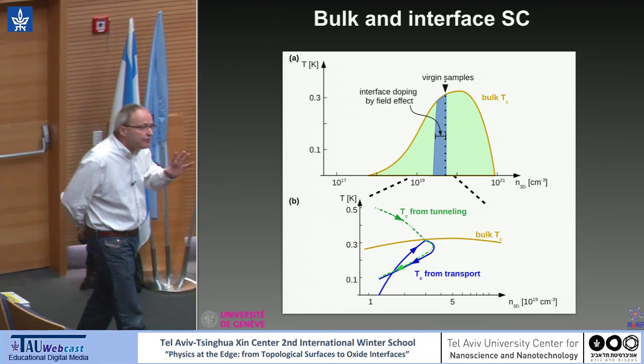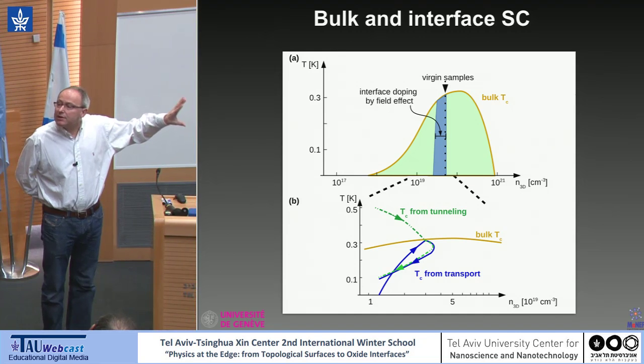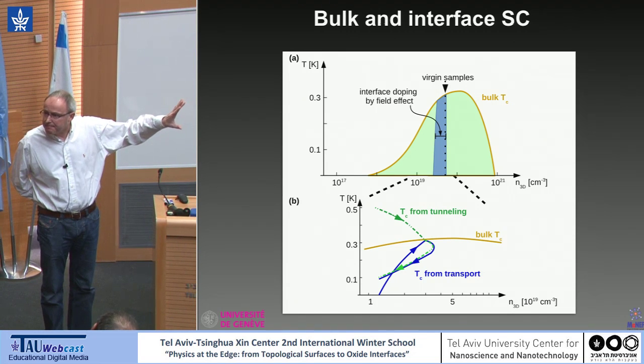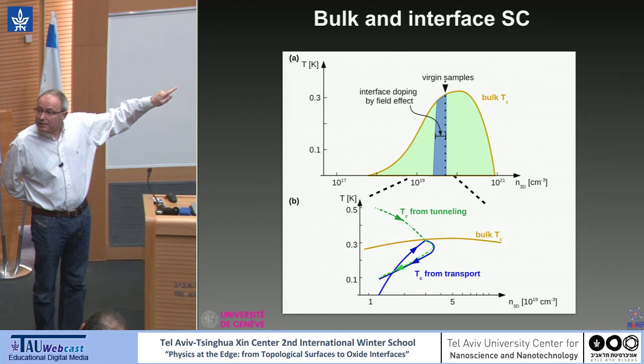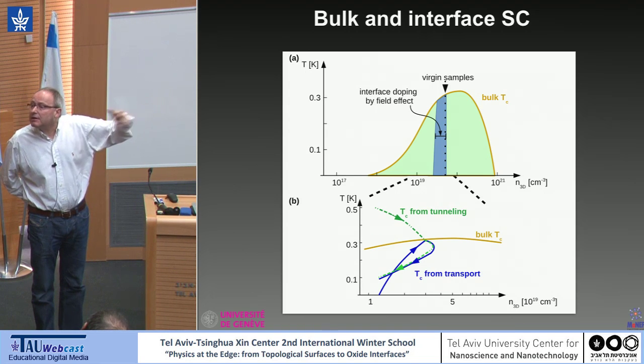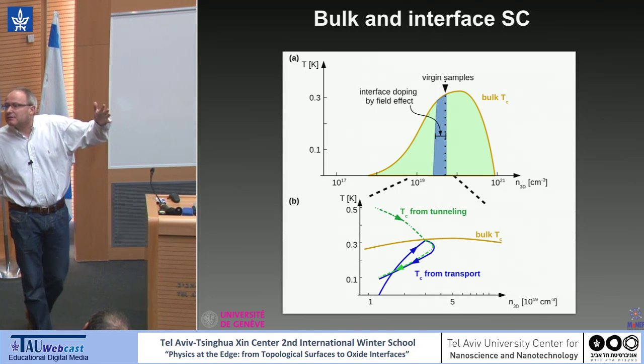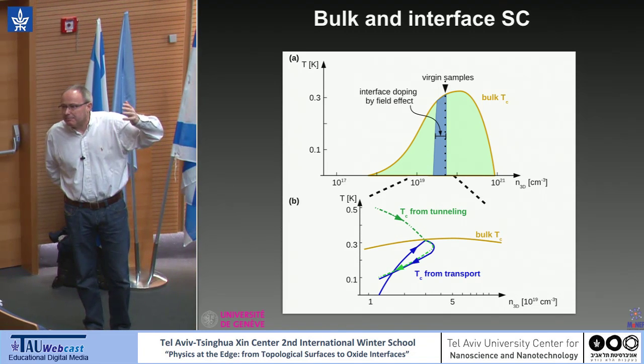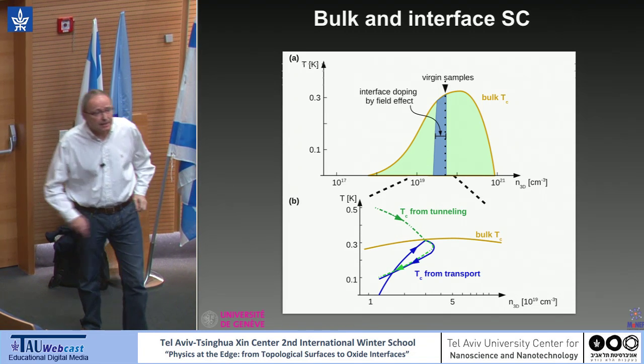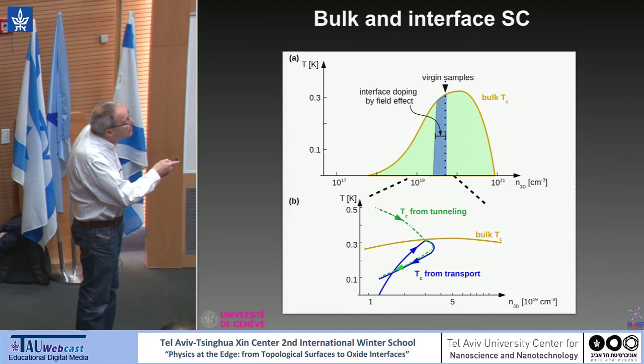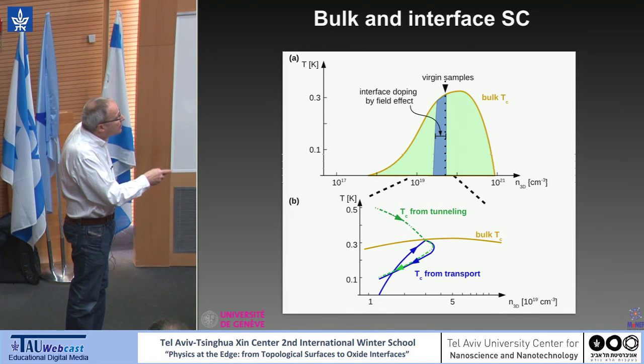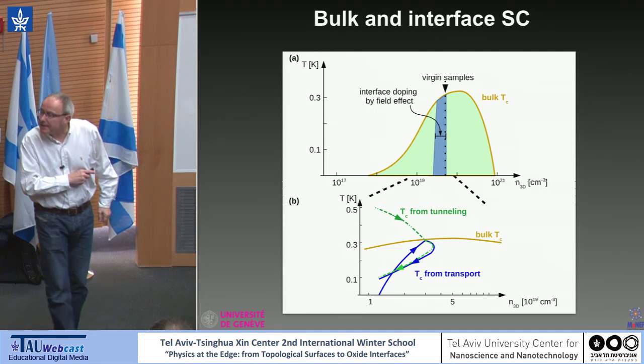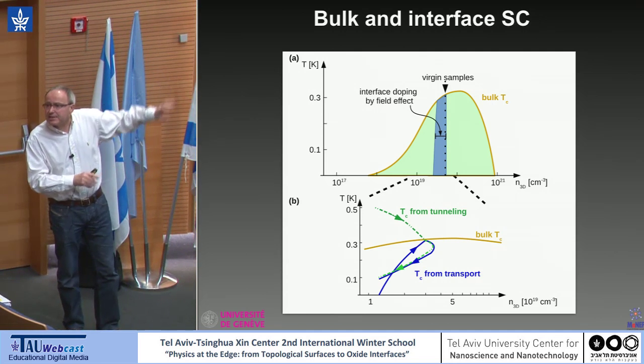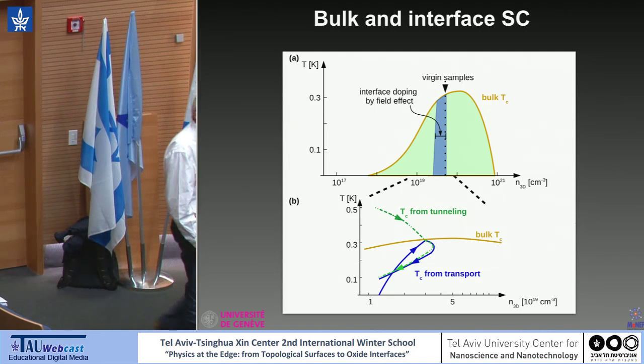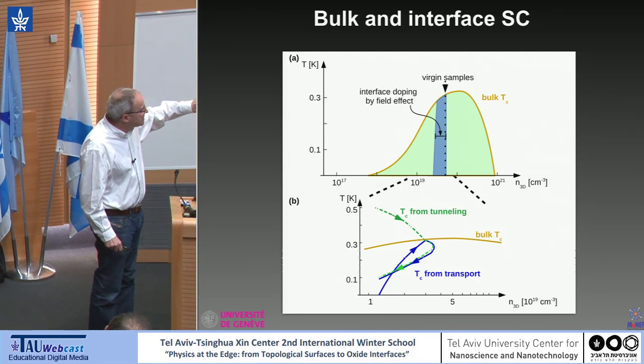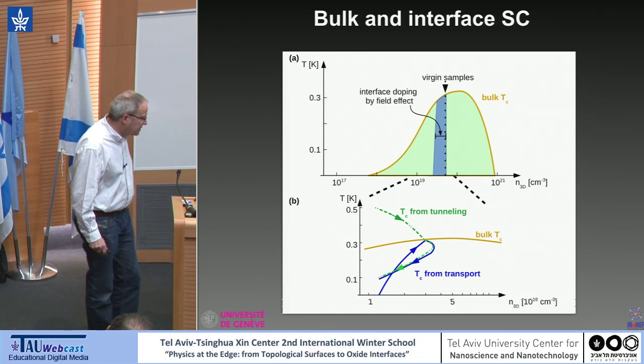So you're completely right. I went too fast. The first phase diagram I showed you was a Kosterlitz-Thouless analysis of TC. When I was comparing to bulk, we use the midpoint, which is more a criterion in line with a mean field TC. So I should have said this. The analysis we did here is with a mean field TC, and this is why I'm comparing this with the delta TC. So it's different from the first phase diagram you saw. Okay, so in short, we don't know yet what is the good answer here.